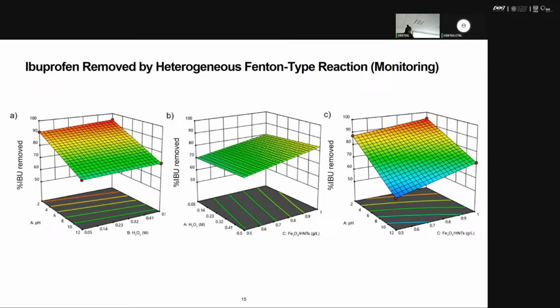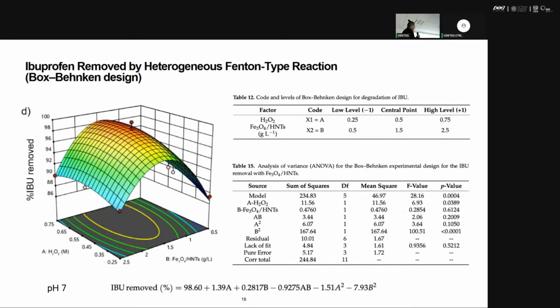And it gives you a response surface methodology. It shows the tendency of how I can use each variable to improve the absorption. For example, here it says that I can increase the quantity of absorbent to improve the mineralization. That is the use of this kind of study, because with a few experiments, I can reduce the doses of each variable, and for that I can use a better experimentation. And based on the previous result, I use some quantities. I use the pH at 7 because the aim of this work is to work in neutral condition, because it's better for previous treatment.